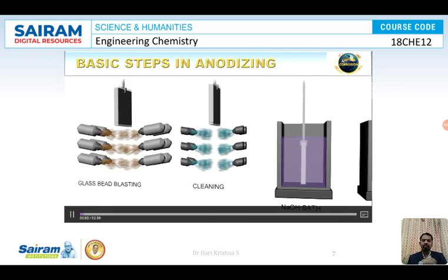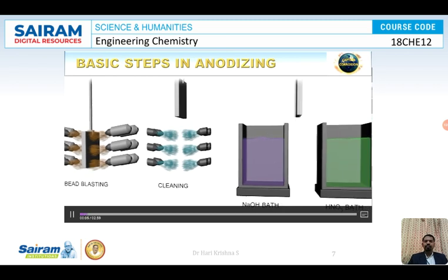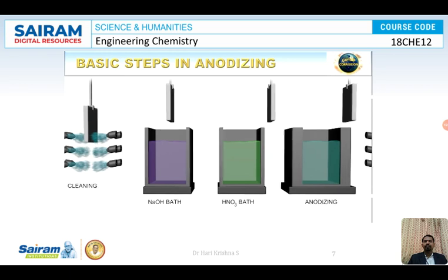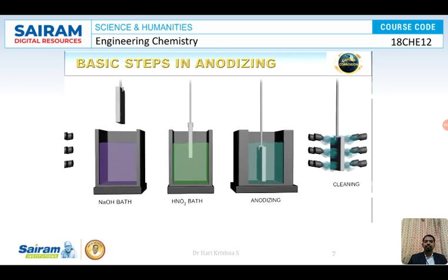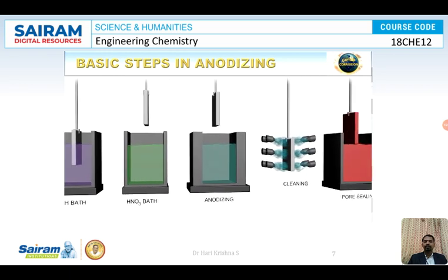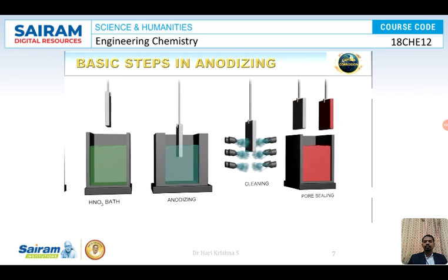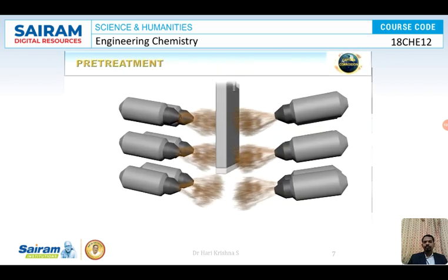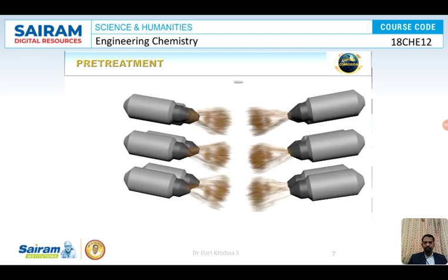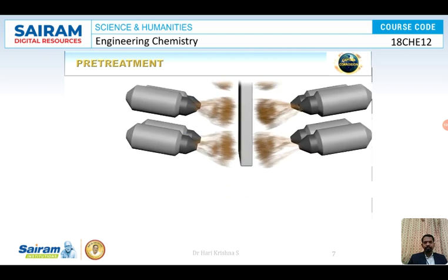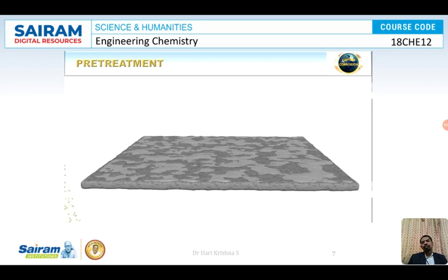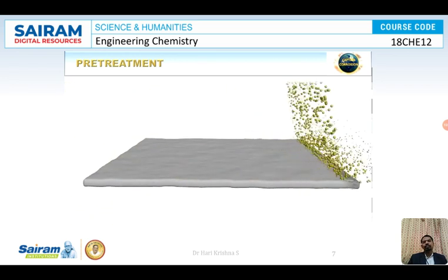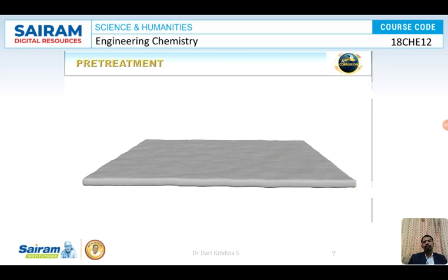Hello science enthusiasts, you are watching a Captain Corrosion video about anodizing, and in this episode you will learn about the basic steps that are required to properly carry out this process. So let's cover them one by one. First, the aluminium substrate is mechanically treated by polishing or blasting with glass beads. This is important because it helps remove the poor quality natural oxide layer and most of the impurities that would hinder the formation of the anodic oxide layer.